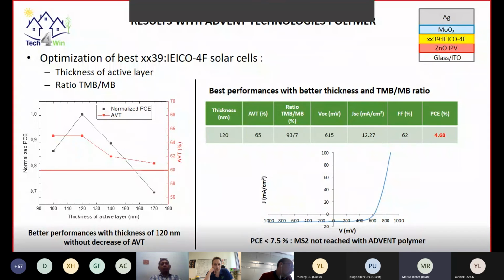We did different optimizations with different layers and different materials. The best organic solar cells are obtained with the xx39 polymer and the IEICO-4F, the non-fullerene acceptor. We optimized the thickness and the solvent for the active layer. As we can see in the graph, the best performance is obtained for a thickness of 120 nanometers, and the transparency of the active layer is about 65%. With all the best parameters, we obtained an efficiency of 4.7% with this polymer, but it is too low compared to the objective of the Tech4Win project.